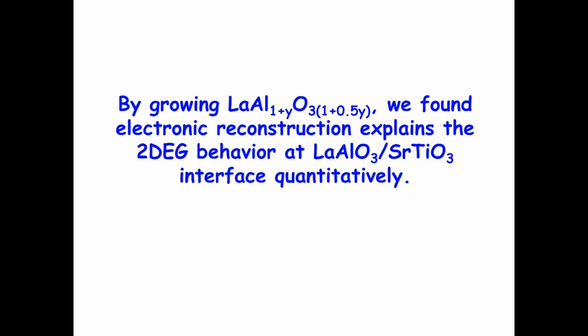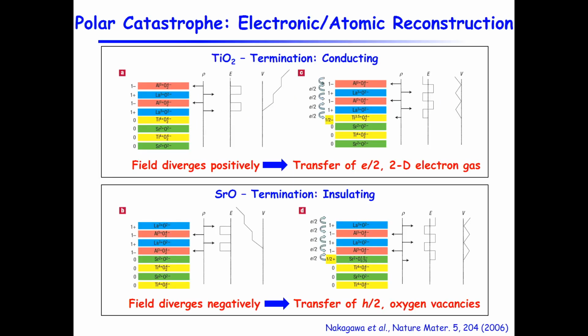The first example, which is mainly what I'm going to tell you about today, is this lanthanum aluminate strontium titanate interface. By growing lanthanum aluminate of different stoichiometry, we have demonstrated that the electronic reconstruction picture is able to explain the two-dimensional gas behavior at the interface.